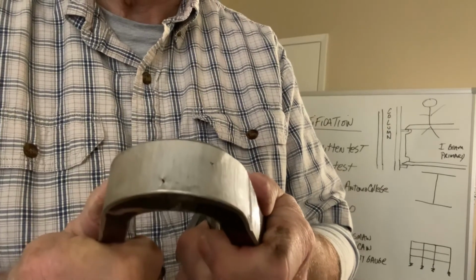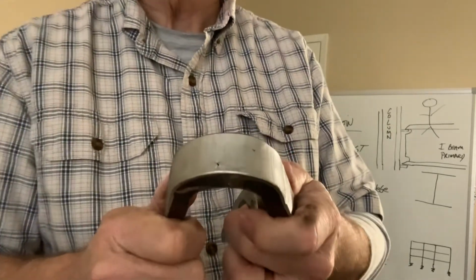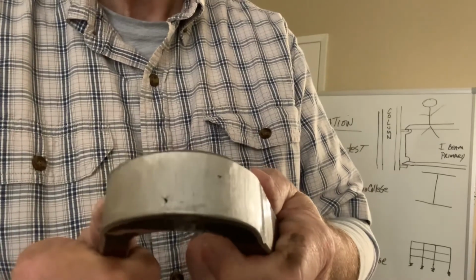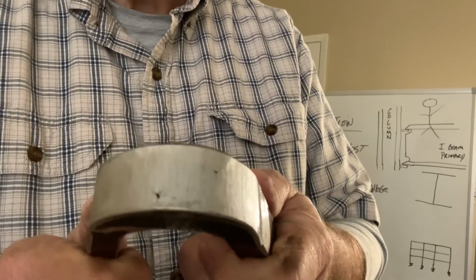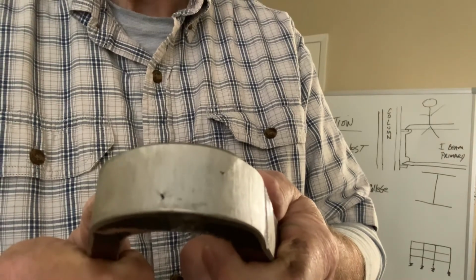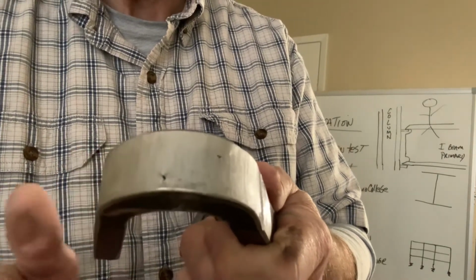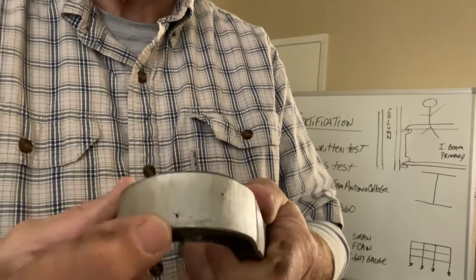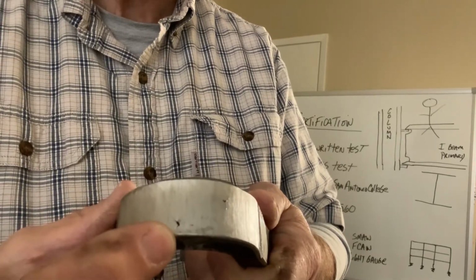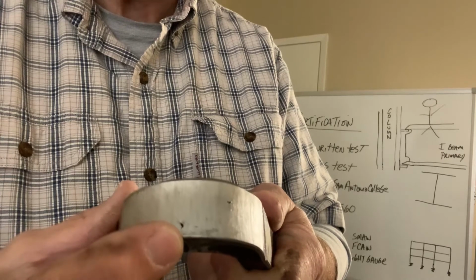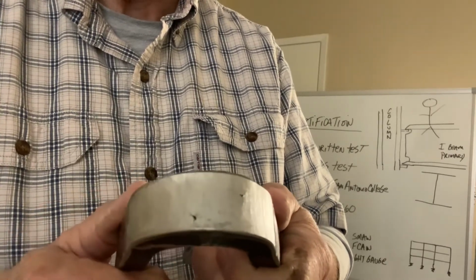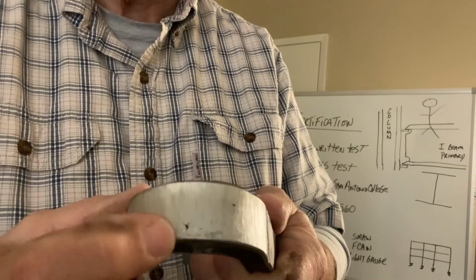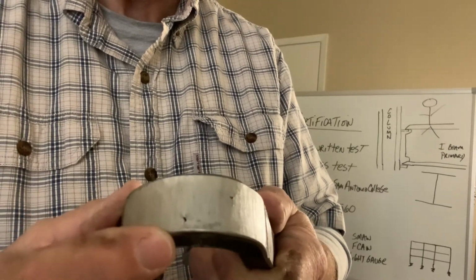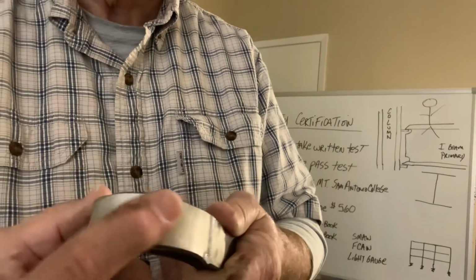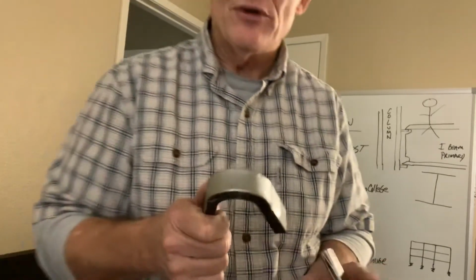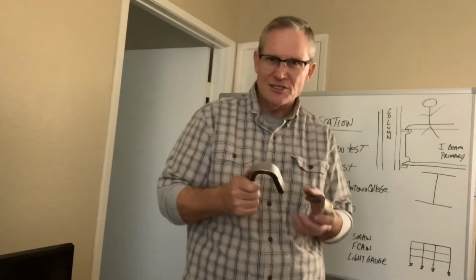Cumulatively, we look at this very, very carefully. We use a magnifying glass and a micrometer to measure each one to make sure that we are within the limits. Anything cracking from the corners doesn't count unless it's got slag in it. So if you didn't clean the slag out of the weld, and the corner opens, that would be a failure. But anything that would open from the edge, if it's clean, wouldn't count. In essence, we read this face, and that determines whether or not the coupon passes.